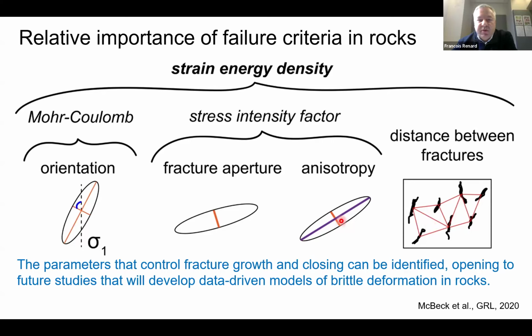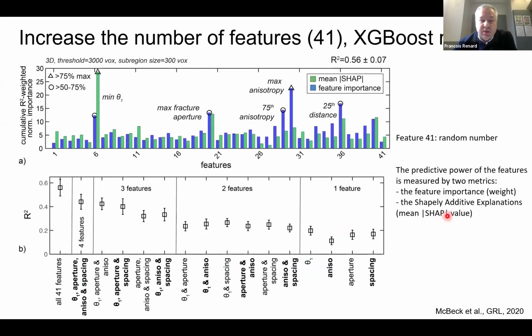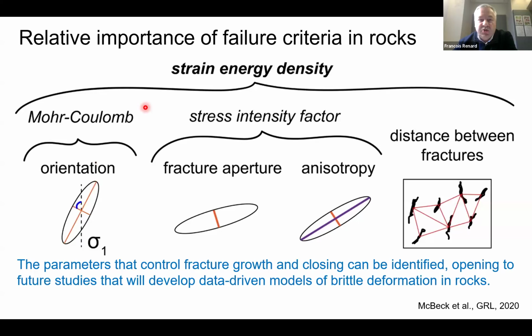So the 4 most important factors here that can predict the distance to failure are a combination of Mohr-Coulomb, fracture mechanics, and strain energy density. And if we combine them together, that's how elastic strain energy is dissipated in the system as damage is growing until system size failure. François, sorry, it's Chris.